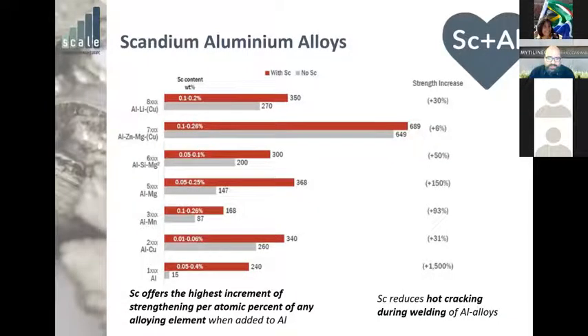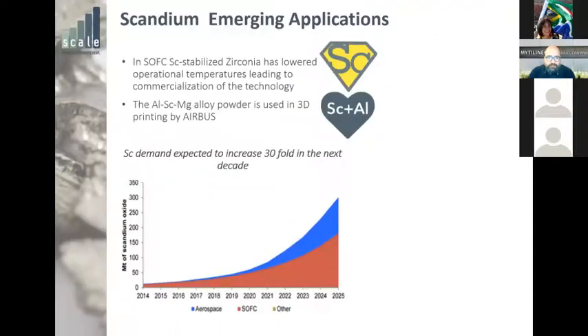You can see that it sufficiently increases the strength of the aluminium alloy just by adding 0.1 to 0.2% in the alloy, and it reduces hot cracking during welding. So it basically hardens your aluminium alloy, especially the aluminium magnesium, the 5000 series, which has an amazing increase with just a small addition of scandium. And so the future for scandium, with two types of applications, especially the solid oxide fuel cells and the use of the aluminium scandium magnesium alloys, which can be used even in 3D printing applications, is that demand is expected to increase 30 times in the next decade.